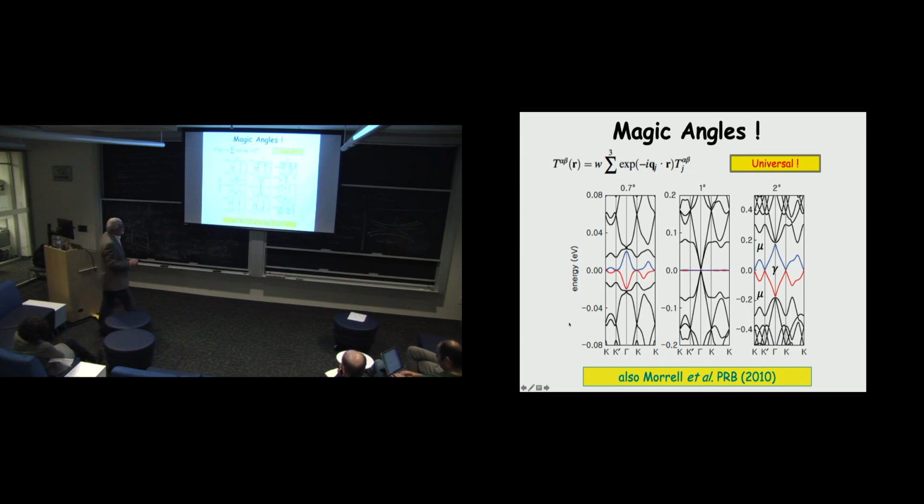So it's important here that we get strong correlation effects not in the limit of very large Moiré patterns, like in the first example I showed you, where the bands just get narrower and narrower the smaller the twist angle, the longer the Moiré period. Here, these flat bands, which will produce strong interaction effects, appear at some intermediate twist angle, some intermediate Moiré pattern length, which is actually very conveniently around 10 nanometers.